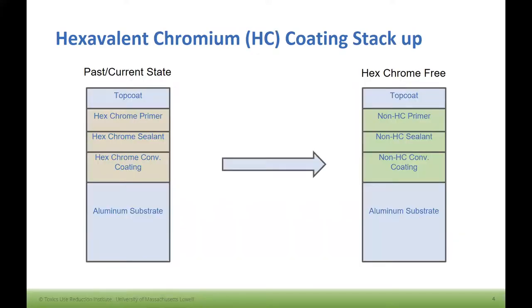So just to give you an idea of a typical coating application stack up in the aerospace defense industry. You've got a substrate, and we're primarily dealing with aluminum substrates. On top of that, you have a conversion coating. Then if there are any cracks or joints, you would have a sealant. And then you would overcoat that with a primer and a top coat. Typically the conversion coating, sealant, and primer have hex chrome as a corrosion inhibitor within them, and we're trying to move to a totally hex chrome free stack up where there is no hex chrome in any of the coating layers.